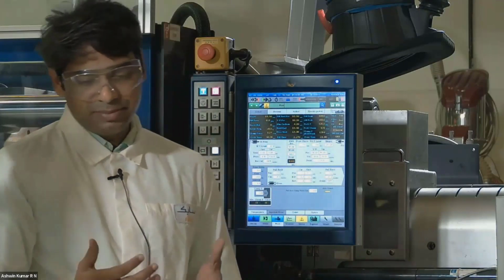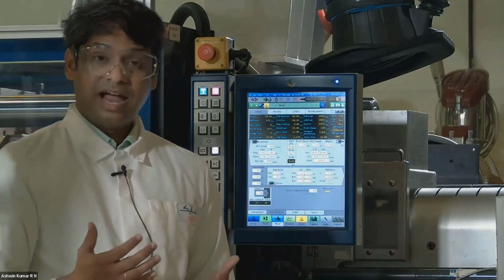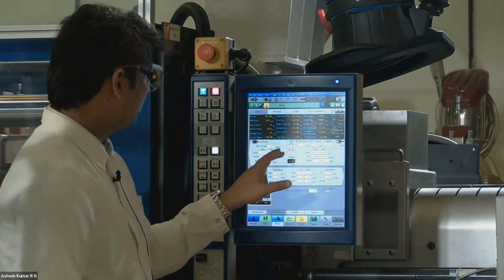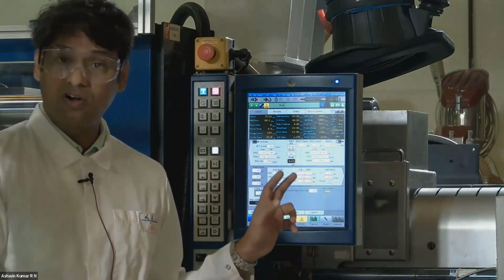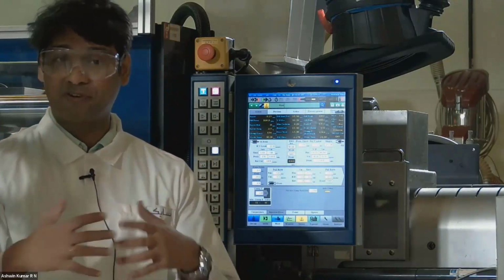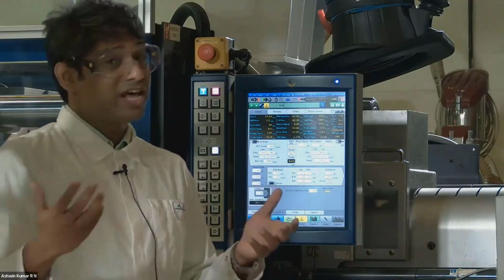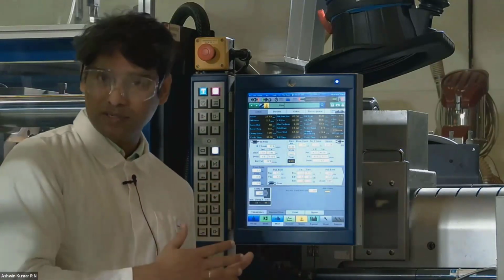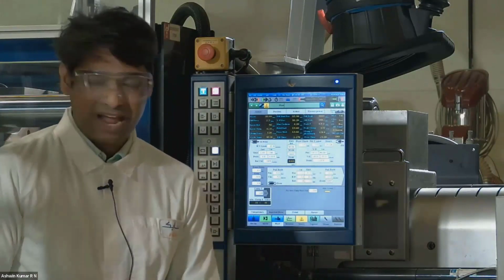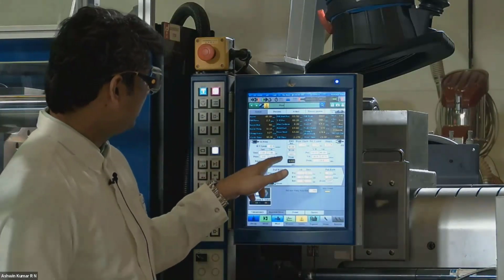And for the packing stage, what we try to do is understand the gate freeze and make sure that we have enough window there to pack the part out. Now in this case, the gate freeze happens at about 5 seconds of packing time, and the packing pressure is something which we estimate on the basis of a cosmetic processing window. We don't want to be on the higher side of the pressures wherein we are flashing the tool, and we also don't want to be on the lower side wherein we are seeing waviness or not a good surface replication from the cavity. So from that, we see about 110 megapascals is what we have set as the holding pressure.